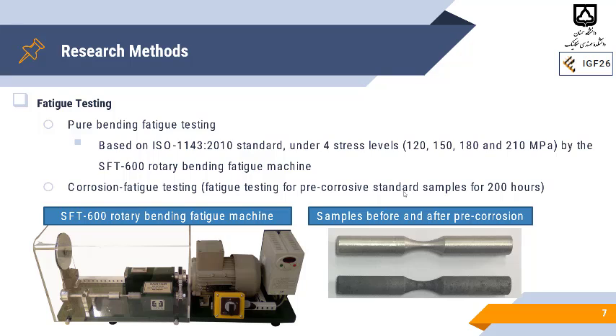And what's happened to our corrosion fatigue testing? We have done fatigue testing for pre-corrosive standard sample after 200 hours in the acid environment. Here also you can see the device, the testing machine, and also the sample before and after the pre-corrosion phenomena. You can see here some pits could be found on the surface of the sample due to the corrosion.